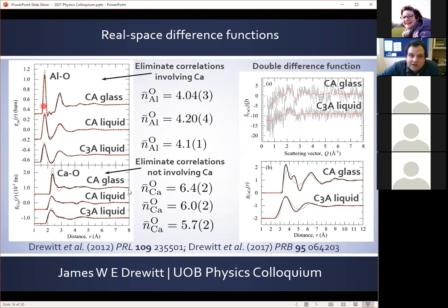The dashed red curves here are from molecular dynamics simulations, and we can see the simulations are in very good agreement with the experimentally measured difference functions, and even on the partial structure factor level. And so this gives us very good confidence in our structural model obtained from simulation.